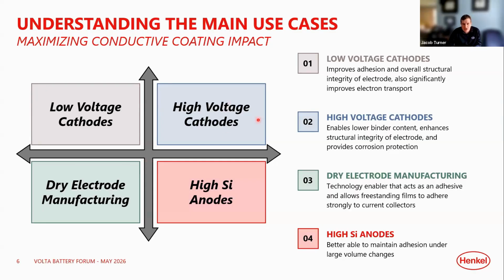As we move towards high voltage, something maybe like your NMC cathodes, again, via an NMP slurry-based process, it kind of reshapes the way we think about using a conductive coating, in that it doesn't necessarily provide the exact same conductivity benefits directly that we see with something like LFP. But what it does do, due to the enhanced adhesion and ability to maintain a high structural integrity of the electrode, is allow for some lower binder content in the active material. So it allows the cell makers to rethink some of the materials on their side, and also provide some of the corrosion protection at those higher voltages. That is one of the areas that we'll dive a little bit deeper into today.